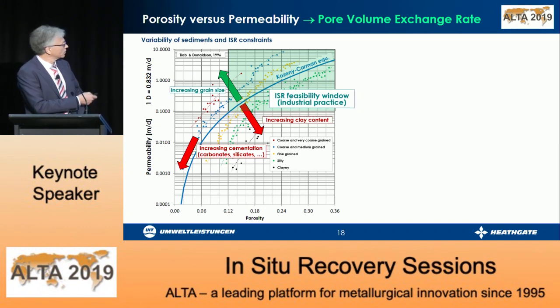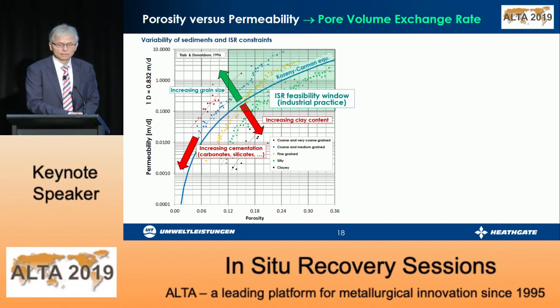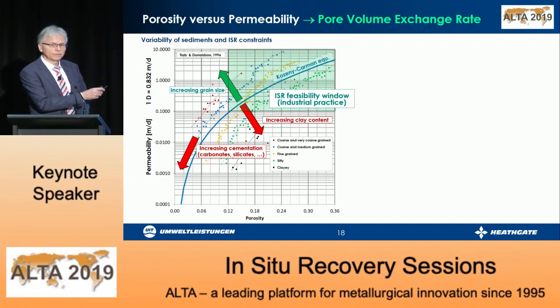You see also that at increased cementation by carbonates or silicates, the permeability decreases. Again, this is our industrial practice. It might differ in some specific cases, but in most operations, we have conditions around this area here, around 1 Darcy, and porosity at least 25%.